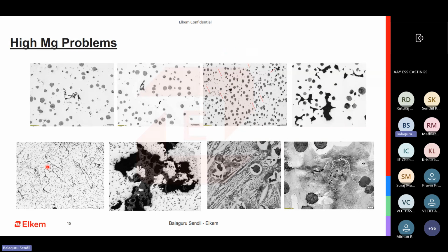And if you are unfortunate and it is high magnesium you are having and you have very turbulent pouring, then the possibility of dross is very high. So dross is something that is formed inside the mold when the metal is being poured into the mold, and at the time it is being formed or solidified in the cavity. If there is some sort of sluggish generation because of either high oxygen and high magnesium, then it is called dross. They typically tend to have a long filamentous appearance.